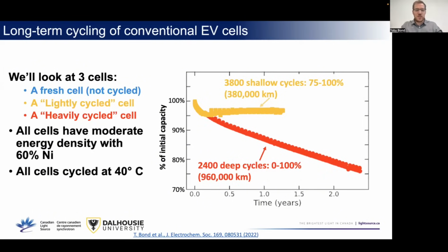These are cells that have moderate energy density. It's about 60% nickel. The more nickel you add, the more lithium you can store, and the more energy the battery can store. But if you have more nickel, you essentially have more of this volume expansion and contraction. We cycled these cells at 40 degrees Celsius, so probably a little bit warmer than the operating temperature, but not that much warmer. It's a typical value. These 3 cells are going to be useful because they cover the range of use cases from not cycled at all, to lightly used, to abused.